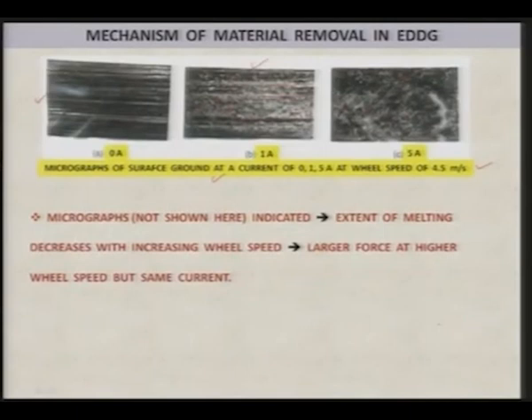and whatever grinding marks we see in the first and second micrographs become invisible, or get overlapped by the crater formation. Micrographs not shown here indicated the extent of melting decreases with increasing wheel speed. I have not shown those micrographs here, but we observed it. Also, there is larger force at higher wheel speed at the same current, which I have already explained in the earlier slide. So, it clearly indicates that both mechanisms, grinding or abrasion as well as the EDM process, are taking place simultaneously in electric discharge diamond grinding.